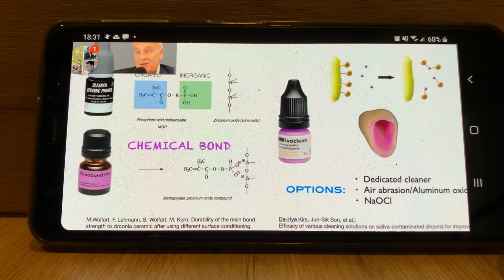Phosphoric acid obviously is not something you want to use. You're just doing the opposite. You're putting phosphate groups back. So I use something like Ivoclean or sodium hypochlorite in a water bath, just to be sure, and that gives me peace of mind that I have really a clean surface, and now I can paint on the primer, the MDP, and I will get the maximal bond that I possibly could.